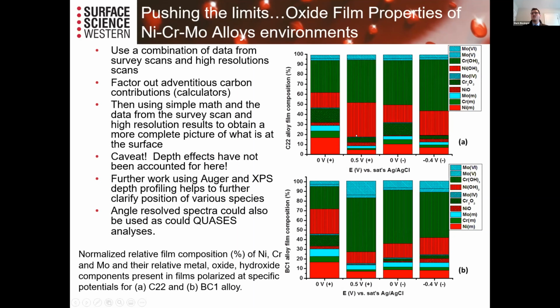And as we go to this next sample, we have much less metal. So first of all, we know that this is a thinner oxide system than this because we're seeing less metal. And if you combine this with things like Auger and XPS depth profiling, angle resolved work, then you can push this even further to say, okay, I have these species present, but now I can tell what's the layering of these species? What's at the surface? What's in the middle of the oxide? And then down into the metals that are present. So the idea is to pull out as much information as you can get from these spectra. So not leave anything on the table, so to say.